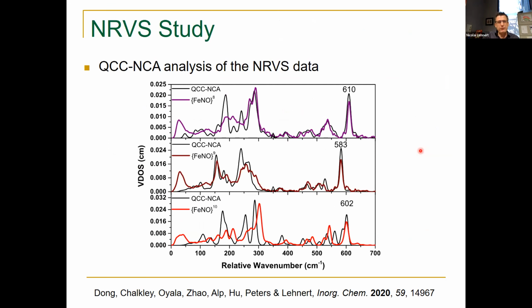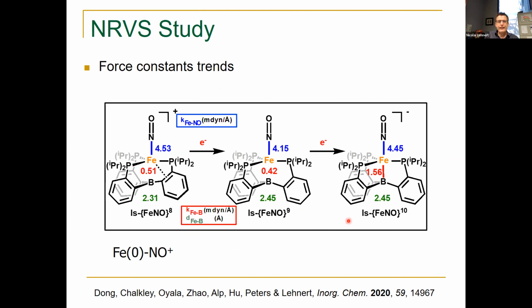And then of course we have NRVS data for the whole series. And what you note here is, remarkably, as you go from 8 to 9 to 10, there is very little that happens with the iron NO stretching mode, which was really not what we expected, right? And so that means that the redox active orbital here does not really involve the iron NO bond, right? Because there is no large effect really on that. So there's got to be another orbital that serves as the acceptor here. We don't have a lot of time, so I want to just cut to the chase here.